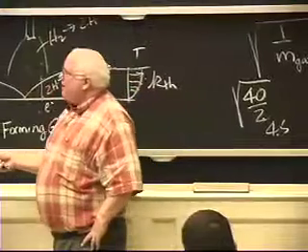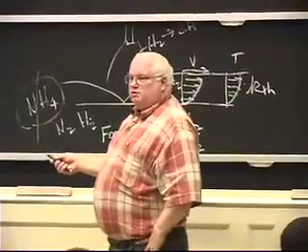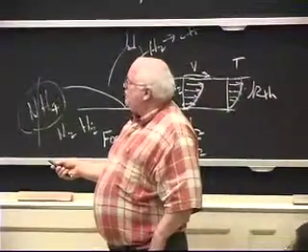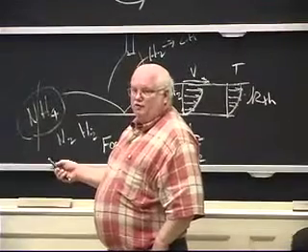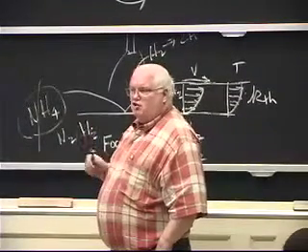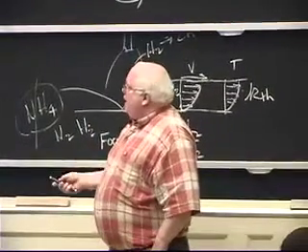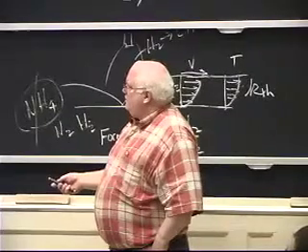They actually have to cool off that tip slightly. So the maximum heat was actually back further, because the electrons at the tip are cooling the tip of that electrode. And they carry that extra heat back down here to the anode.